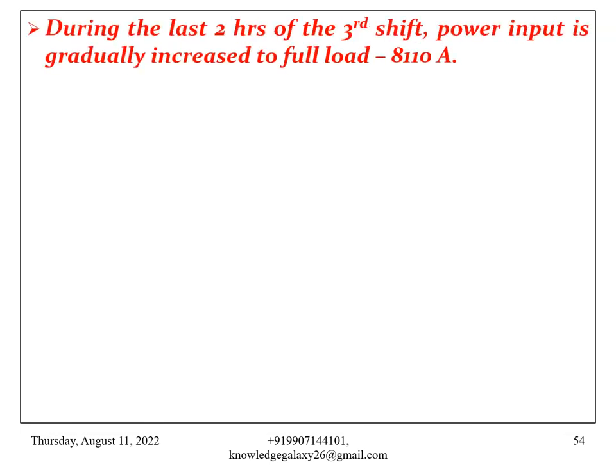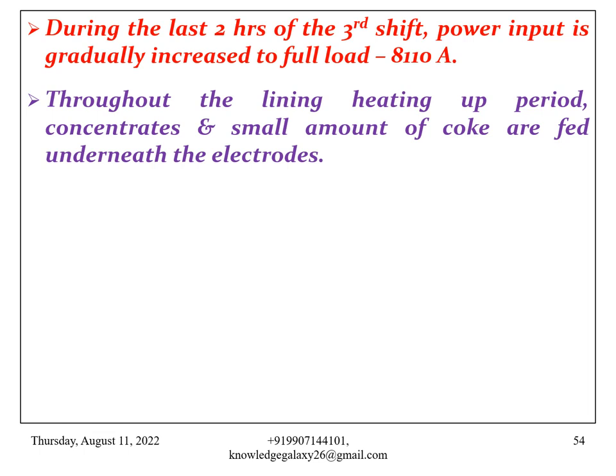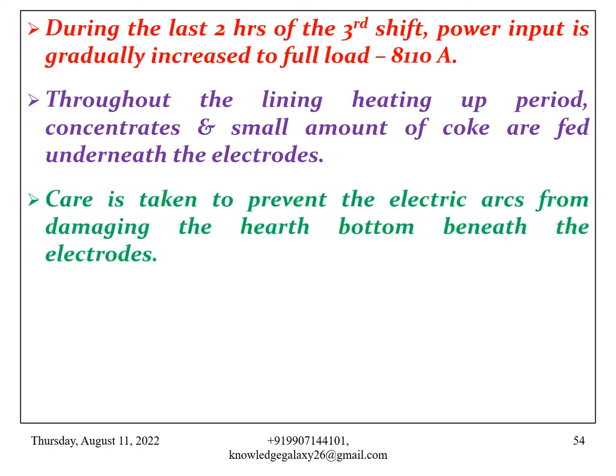During the last 2 hours of the third shift, power input is gradually increased to full load, that is 8110 amperes. Throughout the lining heating up period, concentrates and a small amount of coke are fed underneath the electrodes. Care is taken to prevent the electric arcs from damaging the hearth bottom beneath the electrodes.